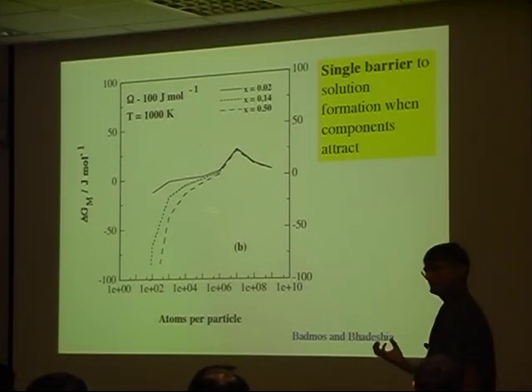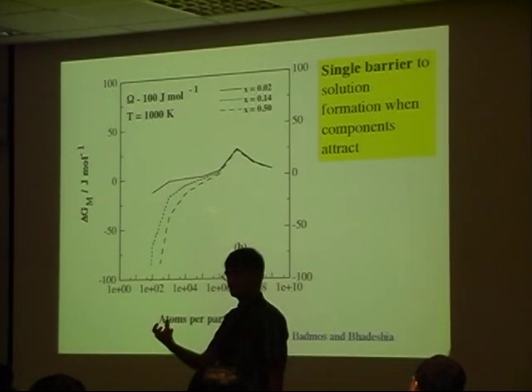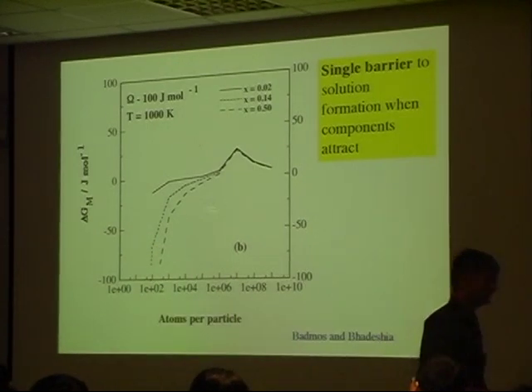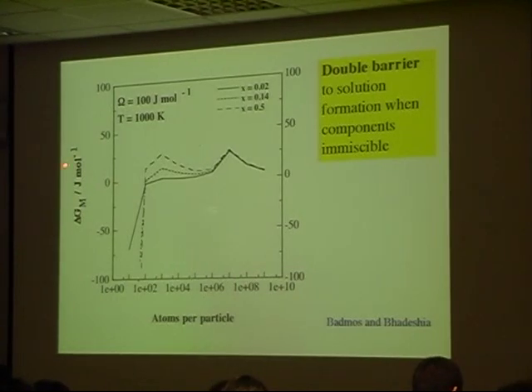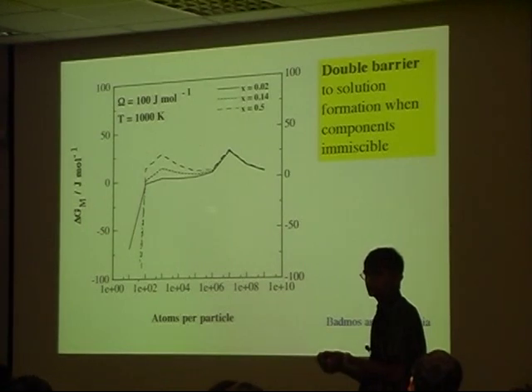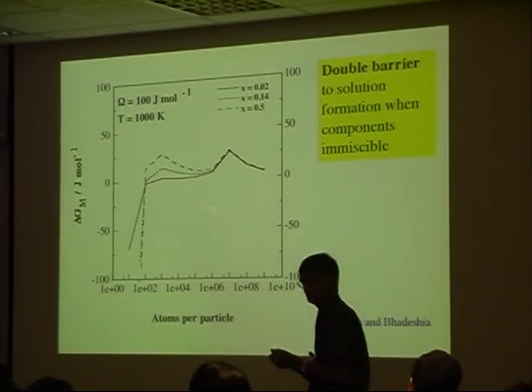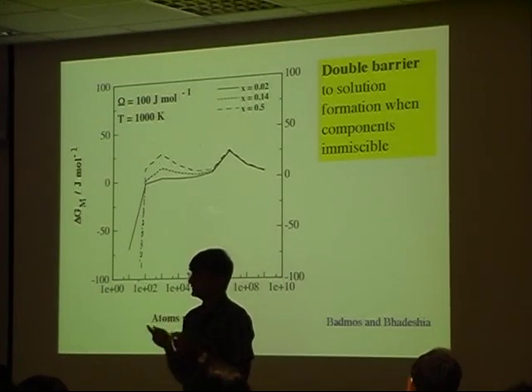If we have a mixture of atoms where the A atoms like to be next to A atoms rather than next to B atoms, then we predict that there are two barriers. You introduce a second barrier when you start to force A atoms to be next to B atoms, even if they don't want to be. Mechanical alloying doesn't allow diffusion. It means you are forcing atoms to be next to neighbors that they don't like. Therefore, you have to do some extra work.